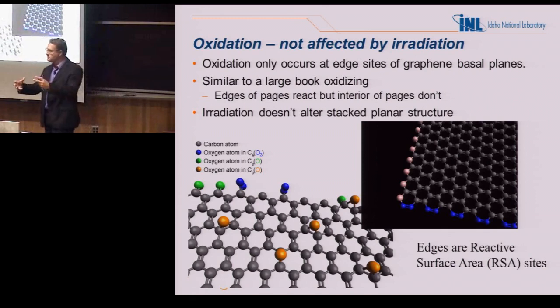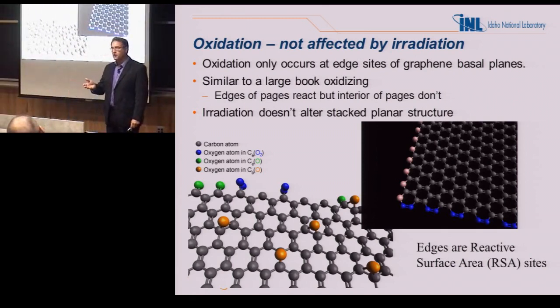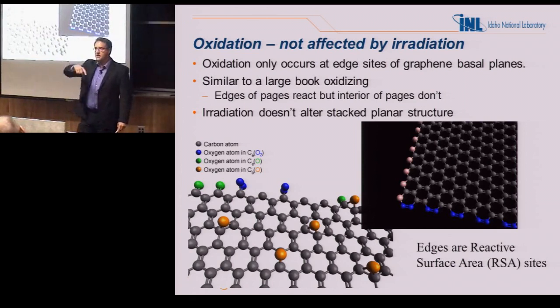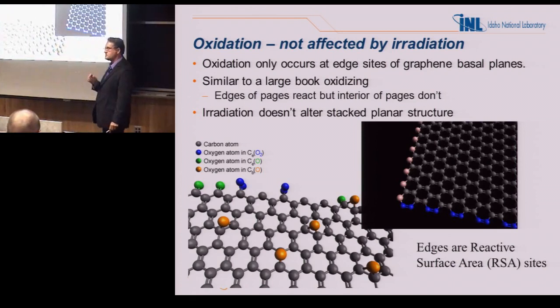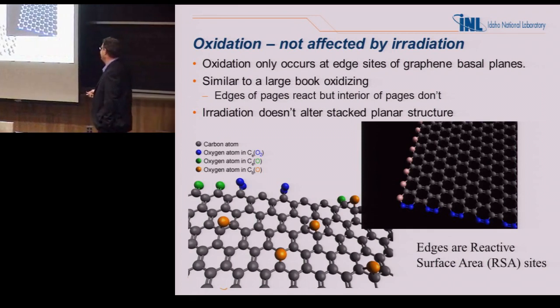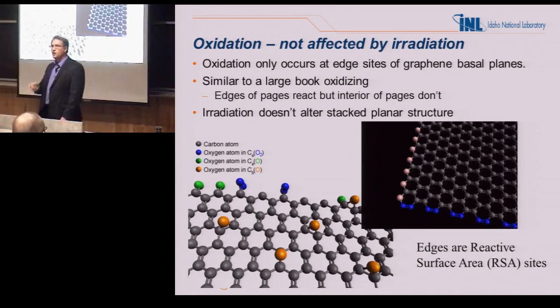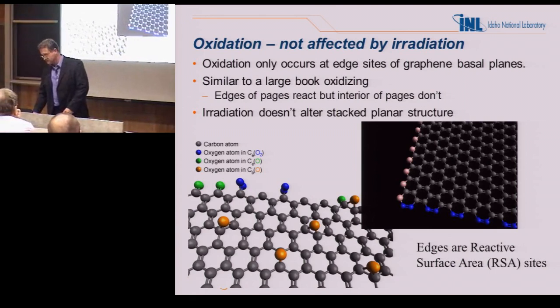So anybody who's gone in, taken a large book, throwing it onto a kindling fire, does it burn? No. All it does is it may singe the edges, but the center of the book stays the same. Okay, you can still utilize it, much to our disappointment. As a consequence, the same thing for the graphite. Now you know why I'm a nuclear engineer. No, so the point is that you don't get anything hanging up or pulling off of those covalent bonds. Why? How could it? It would have to break an enormous number of covalent bonds for it to rip anything out of the center. It can only do it from the edges, and as a consequence, it only burns in one atomic length, and then it goes down to the next one, and it burns another atomic length. It can oxidize, but it can't self-sustain. There's just not enough reactive energy to keep it self-sustaining. Graphite cannot burn. If you want, I have actual videos showing that.